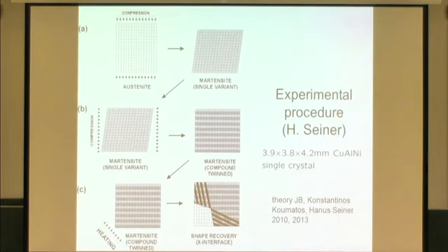So then he heated up this laminate from the corner. So it wants then to form austenite, right? But the calculations show that you can't make a classical austenite-martensite interface with a laminate of compound twins. The only possibility is to make it with a laminate of type 2 twins. So it was conflicted. On the one hand, it wanted to match onto this laminate of compound twins, and on the other hand, it wanted to make an austenite-martensite interface with other twins. And so what it did was a compromise. It produced, therefore, a double laminate, half of one and half of the other.